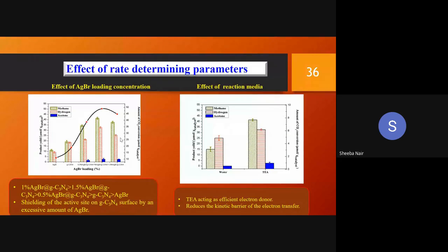You can see the products here: methane, hydrogen, and acetone. Methane was found to be in a higher quantity. Here we never aimed at any selectivity. Mind you, we never aimed at any selectivity. We just performed the experiments as such with the available materials. We were just bothered about the activity here.